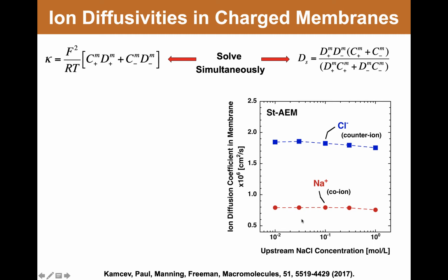If you were to look at sodium and chloride diffusion coefficients just in aqueous solution, the chloride is about 1.5 times as mobile as sodium. It has a smaller sphere of hydration of water around it relative to sodium, and so it makes a more compact structure in water that diffuses a bit more rapidly than hydrated sodium.